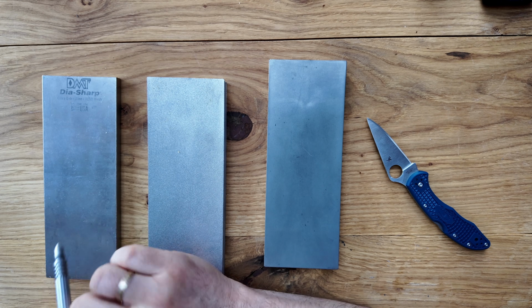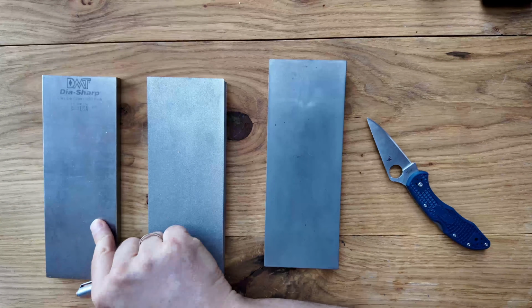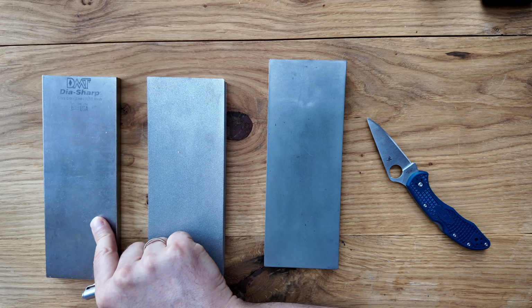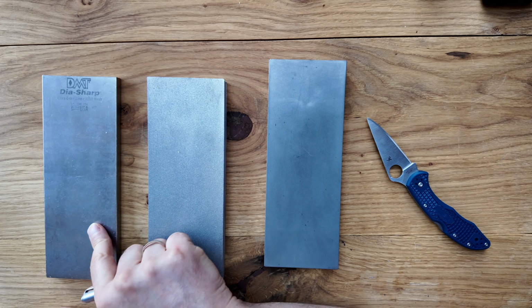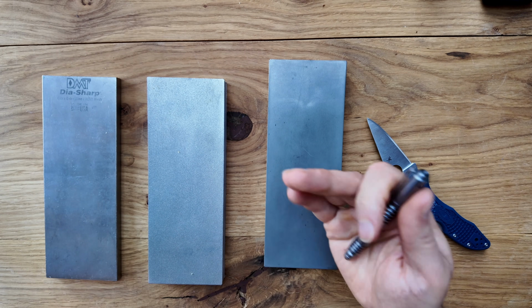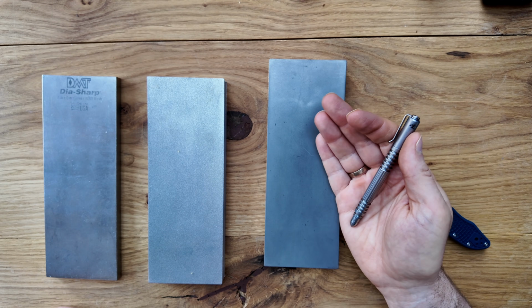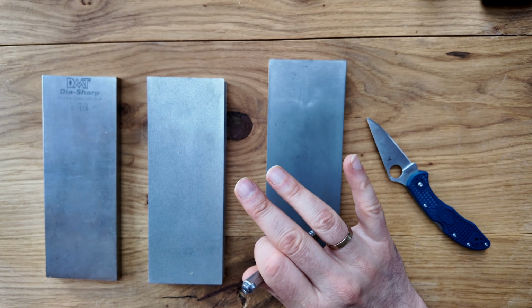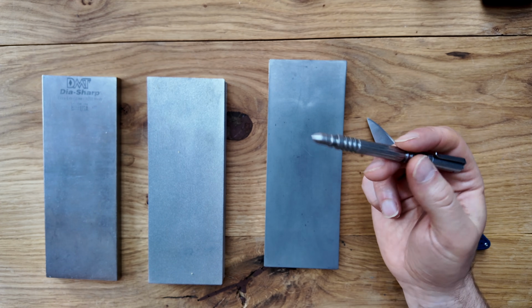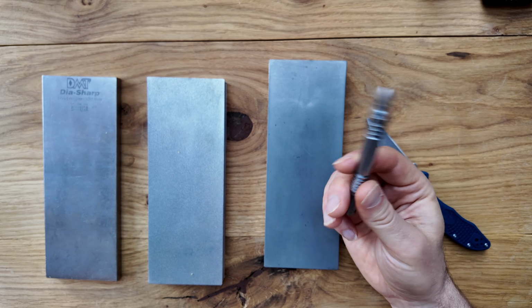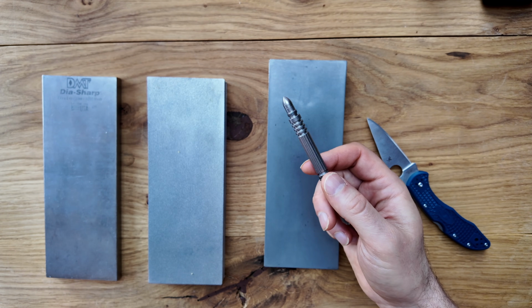I also see some empty gaps in the diamond field and several metallic looking reflective spots scattered across the surface. So the honest answer is, this stone surface is not as clean as the 4000. There are things on this plate that should not be there, or at least should not look the way they do. But a stone can look imperfect under magnification and still perform quite well. What matters is whether any of this actually shows up in the edge.